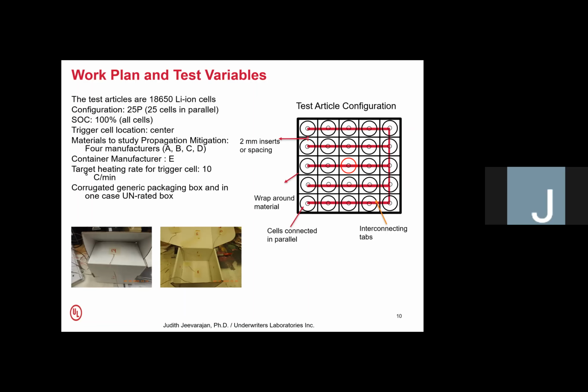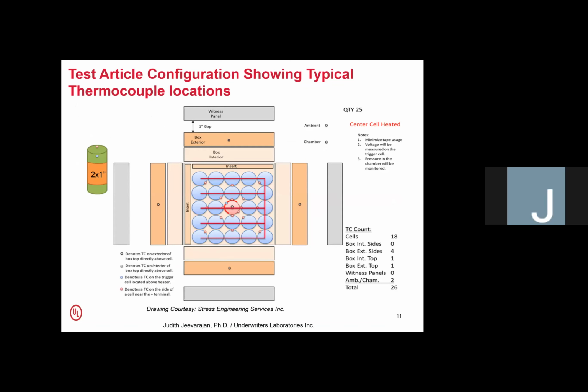We looked at 4 different manufacturers with different materials, and we also looked at a container manufacturer. In order to not disclose the manufacturers' names, I have them as A, B, C, D, and E. Our target heating rate for the trigger cell was about 10 degrees C per minute. And again we looked at a worst case configuration by choosing a generic packaging box. This is not a UN rated box, but it's a box that we usually get cells in when you buy cells online. So we wanted to have a worst case situation all around. The next picture shows our thermocouple locations. We had anywhere from 17 to about 26 thermocouples used in the test.